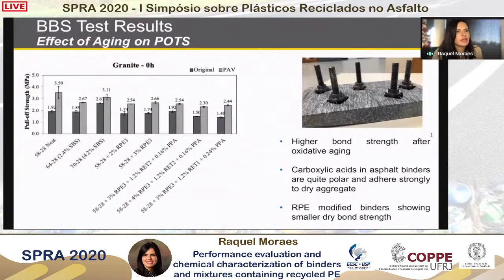First results that we have over here are the effect of aging on the bond strength of the recycled plastics. And we can see here we have POTS results that were collected with the BBS on the original binder and after PAV. And we can see that a higher POTS value, or a higher bond strength, is observed after oxidative aging. And one explanation for that is that the carboxylic acids that are present in the asphalt binder increase because they are products of oxidation, and they are quite polar.